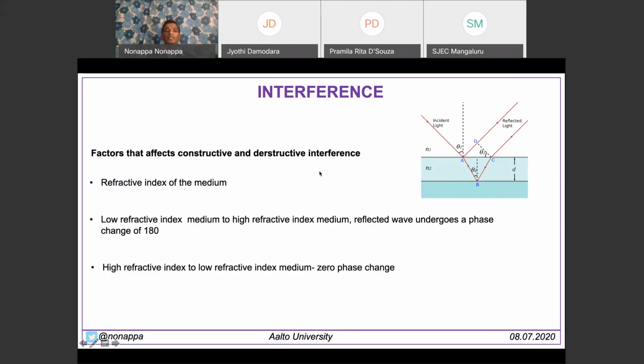There are three different factors that it depends on: one is the refractive index of the medium, the number of layers, and the thickness of the layers. As I said, if I have a low refractive index, which means air, it is one, and a higher refractive index medium, like water, air is one, water is 1.33. It means that the light travels 1.33 times slower, much slower in water compared to air. Then we see a phase change of around 180 degrees. Then there's a perfect constructive interference.